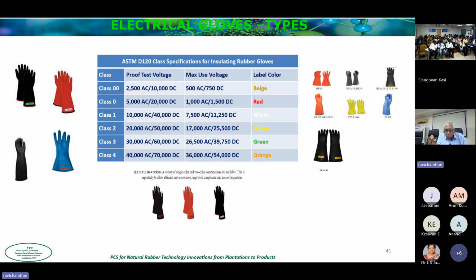And then we were able to introduce ultra low protein rubber, and we found that the voltage ability went up by almost 20-25%. So many of the electrical glove manufacturers use protein-free gloves, because the presence of protein allows for little migration of moisture into the glove over time. As the glove gets older, there will be more moisture into the glove. So the ultra-low protein allows for the glove to be protein-free and no ingress of moisture during the service life of the glove.